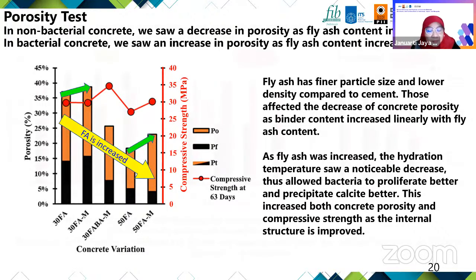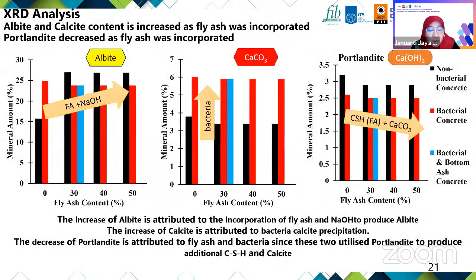Albite, as a product of aluminosilicate, reacts with the reaction product between sodium hydroxide and fly ash in the early age, and increases as the fly ash is present in the mixtures. The product of bacteria was also found, as we can see that there is a calcium carbonate content in the result, especially with the red specimen containing bacteria.